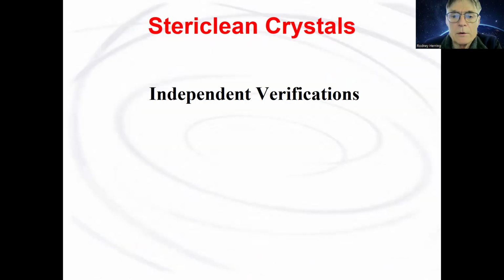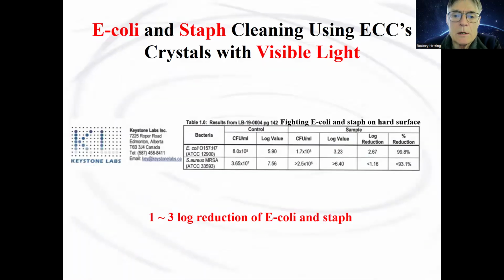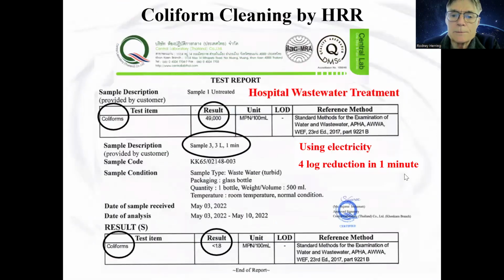We've had several independent verifications. This is with a government-approved lab in Edmonton, Alberta. It's Keystone Labs. We find that it removes the E. coli and staph. This is the visible light activation of the crystals, and it reduced it by 1 to 3 logs. So you can see reduction of 99.8% and 93% for the staph.